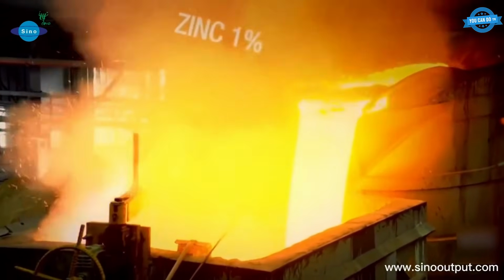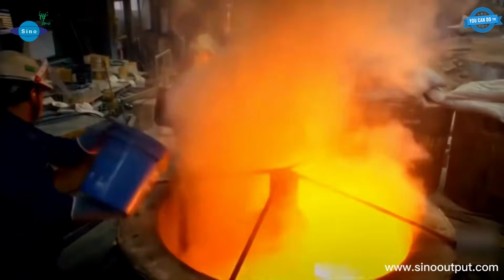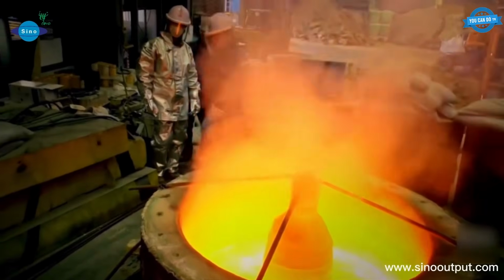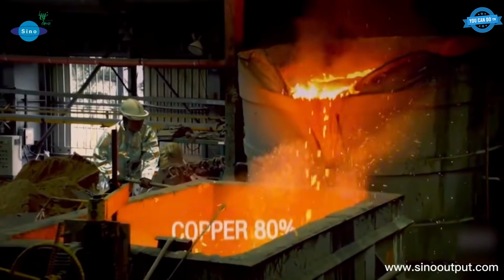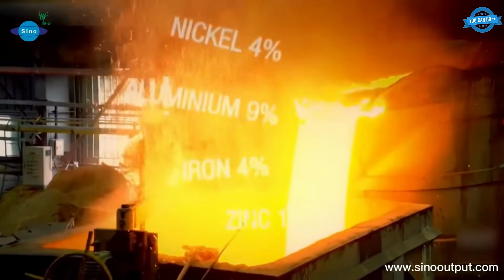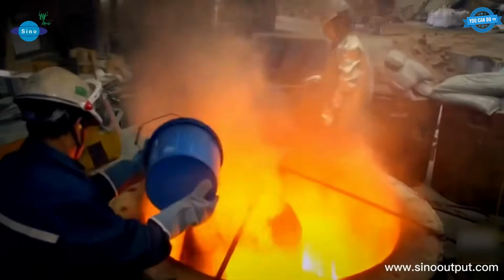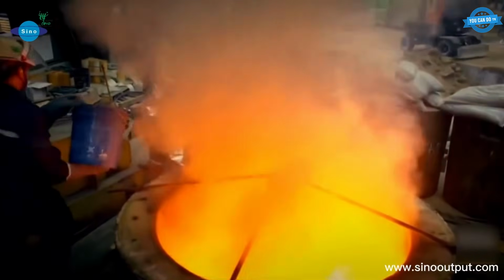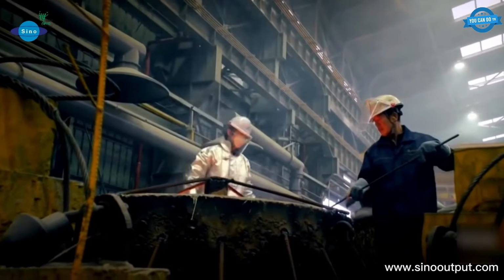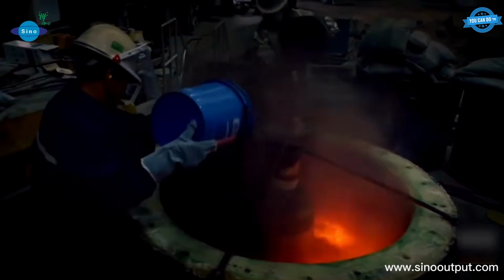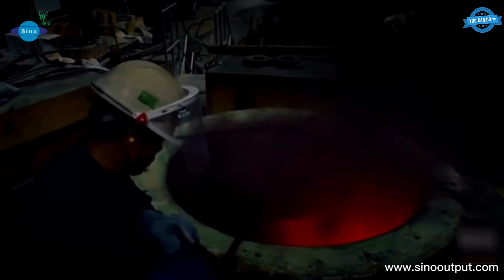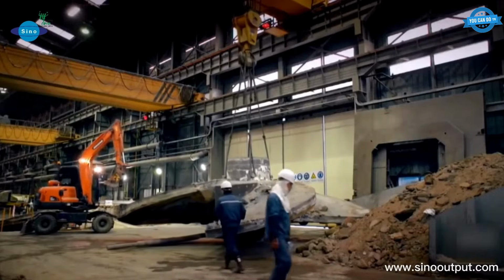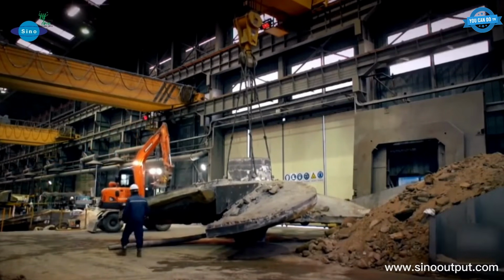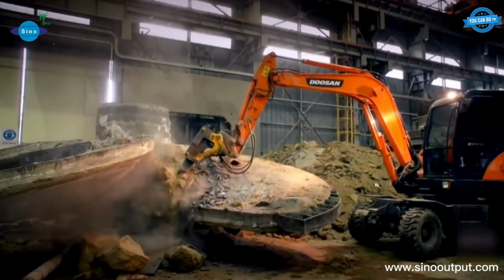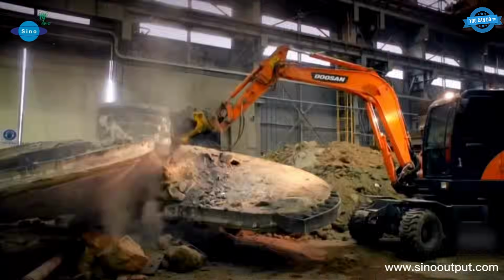Inside an industrial foundry, workers run a high-temperature furnace to melt the alloy that will become the blades. The mix is held to a precise composition: 80% copper, 9% aluminum, 4% nickel, 4% iron, and 1% zinc, a nickel-aluminum bronze recognized for its resistance to cavitation in seawater. The molten alloy is poured into the prepared mold under technical supervision. After the metal has cooled and solidified, the heavy mold block is moved aside and a tracked excavator with a hydraulic breaker chips away the surrounding sand and slag.